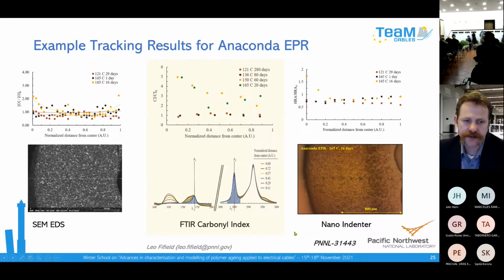of the material. Here are a few techniques that have been used historically to look at this inhomogeneous aging, meaning the aging doesn't happen the same throughout the material. These are through the thickness of cable insulation. These are low voltage cables, so the thickness of the insulation is on the order of a couple millimeters. And here's the interior and the exterior of the insulation sample. These were aged with the conductor removed, so we have aging on the inside that's similar to the outside.